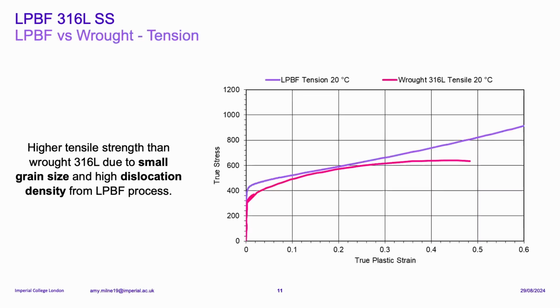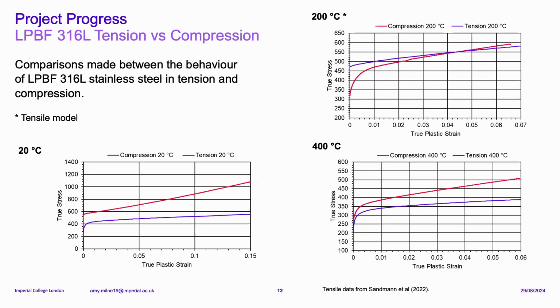So jumping to the wrought material, this is LPBF 316L being compared to wrought 316L, and you can see that there's a higher tensile strength for the LPBF material, likely due to the small grain size and the high dislocation density from the successive welds and the fast cooling rates, which give you incredibly small grains. And now I'm going to compare both laser powder bed fusion tension and compression samples.